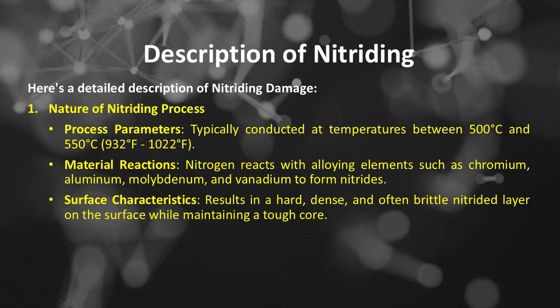Number 1 is the nature of the nitriding process. Process parameters: typically conducted at temperatures between 500 degrees Celsius and 550 degrees Celsius, or 932 degrees Fahrenheit and 1022 degrees Fahrenheit. Material reactions: nitrogen reacts with alloying elements such as chromium, aluminum, molybdenum, and vanadium to form nitrides. Surface characteristics: results in a hard, dense, and often brittle nitride layer on the surface while maintaining a tough core.